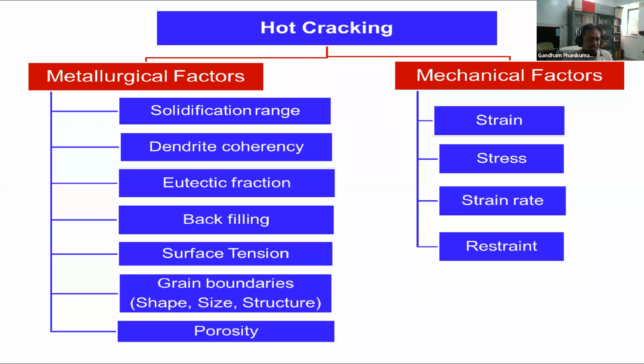Eutectic fraction is basically telling you how much liquid is available in the last stage of solidification, so that it can go and fill the regions in between the dendrites and make the solid compact, without any gap in between, like a void, which is basically a crack. Backfilling is the ability of the liquid to flow between two grains or two dendrites so that it can fill it. Sometimes it doesn't happen because of an intermetallic formation that is preventing the backfilling. And then surface tension, because if it has wetting problems, then you have that issue also. But of course, in superalloys, that's not a very serious issue.